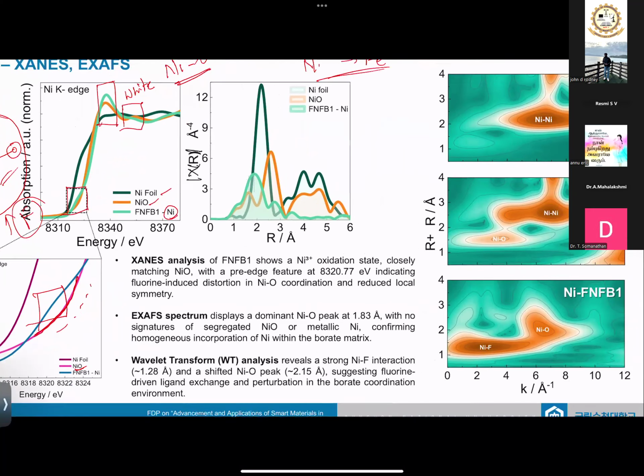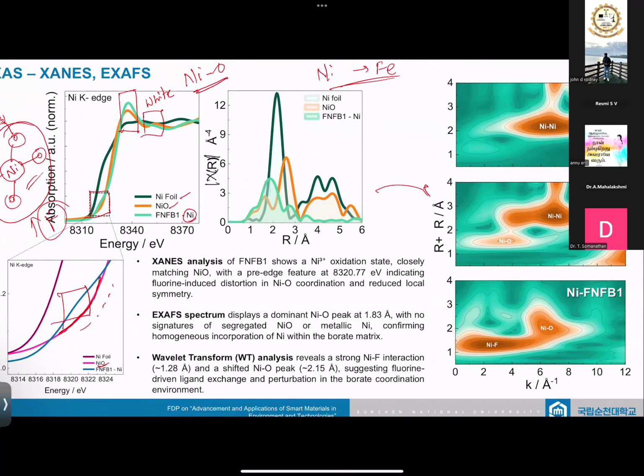And then we did the contour-based studies based on the EXAFS. Based on EXAFS, we did the contour study where this is the nickel foil data, with this contour area stating the nickel-nickel bonding, and this area specifying the nickel-oxygen bonding. We can see that the nickel-oxygen bonding is slightly shifted to the higher region, and also there is a huge bonding nature which is being denoted here, which is being shifted much further, which is not really a nickel-oxygen bond, which confirms that it's a different bonding nature. So from this we can assure that the nickel is the atom that is being bonded to fluorine. This contour area has been achieved because of nickel bonding to fluorine.